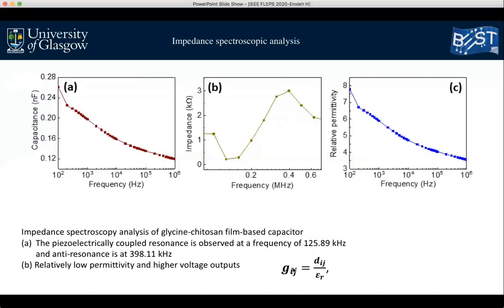So according to this formula, g is inversely proportional to the dielectric constant. And materials such as PZT have a very good piezoelectric coefficient. They have a high d, so they also have a higher dielectric constant. But in terms of organic materials, since the d piezoelectric coefficient is lower, a low dielectric constant is an advantage to have a higher voltage output.